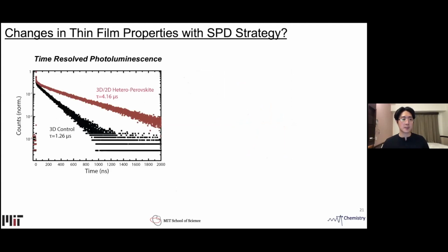So then how does the SPD strategy affect thin film properties? We first perform time-resolved photoluminescence to have a better understanding of its carrier dynamics. By fitting the long component to a mono-exponential, we see about a 3-fold improvement in the carrier lifetime, which can be attributed to reduced non-radiative recombination.